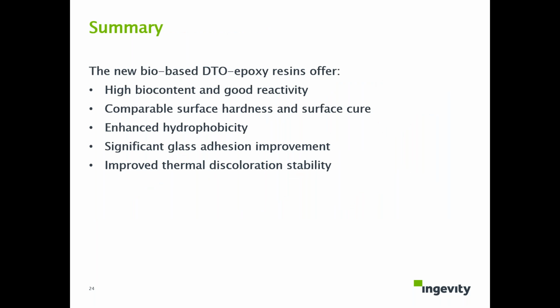So, summary: the new bio-based DTO-epoxy resin offers high bio content and good reactivities, comparable surface hardness and surface cure, enhanced hydrophobicity and significant glass adhesion improvement, and improved color stability at high temperature.